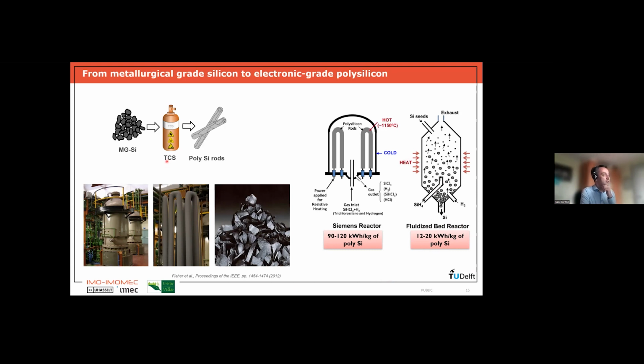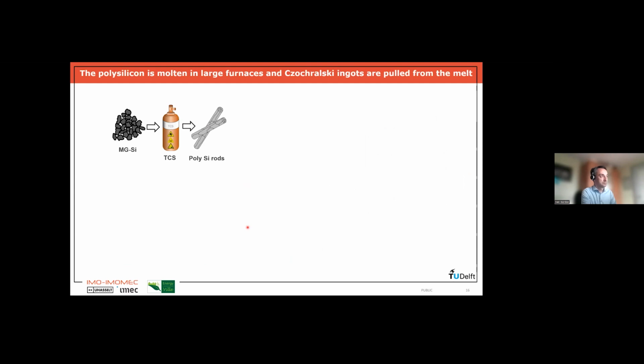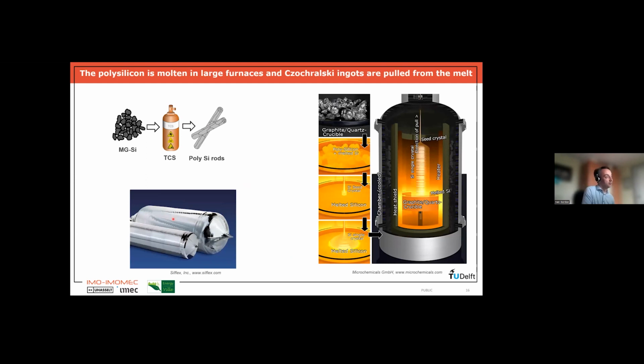So in the end, in this first step, the so-called Siemens process, we go from gas phase to polysilicon rods. Now, these polysilicon rods are not yet wafers, so we cannot use these rods to make solar cells. So typically what is done, these polysilicon rods are crunched into small parts, which are shown here. And then we go to the next step, which is we are going to melt these polysilicon pieces, and we are going to grow an ingot. So here I will focus on monocrystalline silicon, and for making monocrystalline silicon ingots and wafers, typically the Czochralski process is used. That is demonstrated here. So in the end, we start from this polysilicon material, and we end up with this kind of monocrystalline silicon ingots.